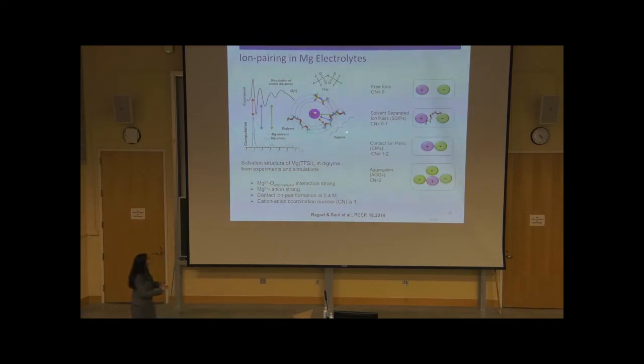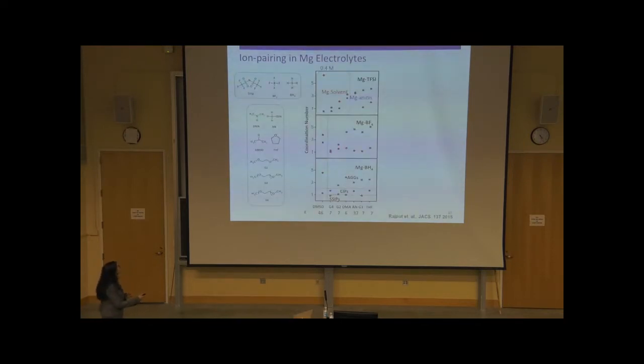Now, by knowing that magnesium has such a strong tendency to form ion pairs, we further investigated this degree of ion pair formation by preparing an electrolyte matrix where we considered different anions and several different solvents, where the solvents exhibit a range of dielectric constant as well as linear and cyclic geometry. And we found that overall magnesium has a very strong tendency to form ion pairs or aggregates in the solution.